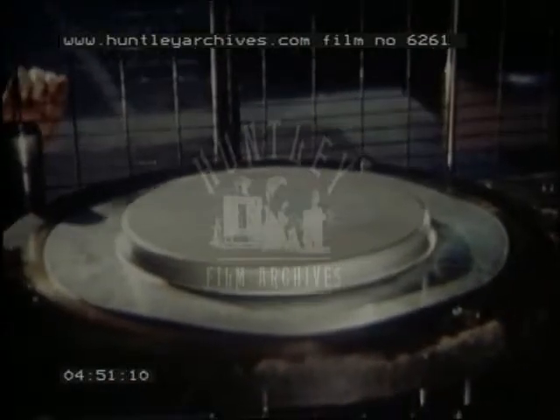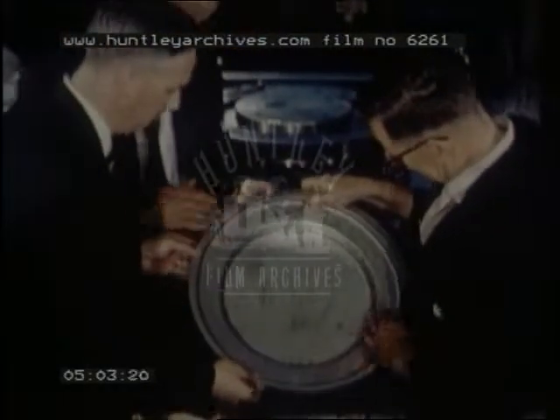You will have noticed that a square of brown paper is placed under the blank for the first stage pressing. It was found that such a procedure on this particular press gave the consistent high standard of pressing required. The excellent surface finish of the blank has been maintained, and wrinkling prevented. This then is the base of the tub, produced on a medium-powered single-action press.